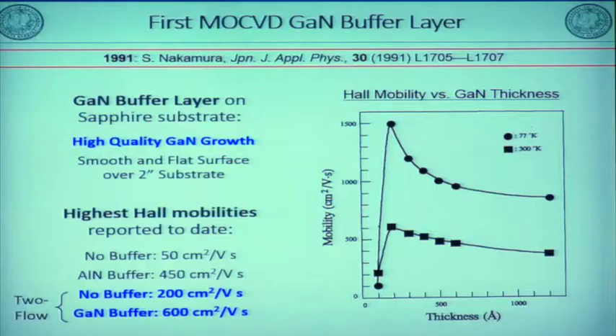The big reason: before my invention, Professor Akasaki always showed the best result in the world. But after this invention, I could always show the best result in the world in this field. For example, undoped gallium nitride growth: Professor Akasaki got the mobility, this is electron mobility, the higher the better. With no buffer layer it is 50, and using an aluminum buffer, they got 450. But in my case, using two-flow MOCVD, with no buffer it is 200. And I invented the gallium nitride buffer, and the mobility is 600. Mobility, the higher the better.